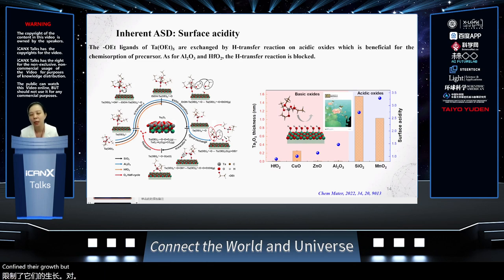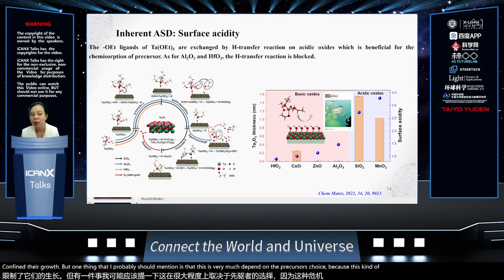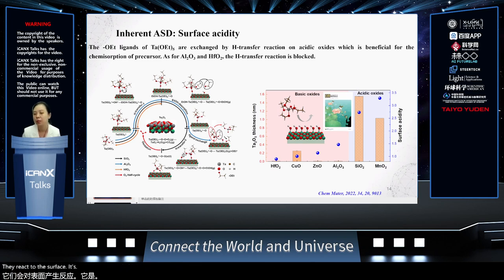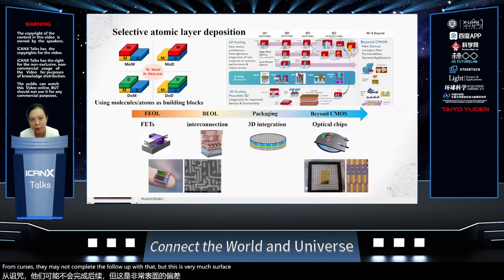But one thing that I definitely should mention is that this depends very much on the precursor choice, because these precursors react with the surface through this kind of mechanism. If we change to another type of tantalum precursor, it may not completely follow this. So this process is very much surface dependent.